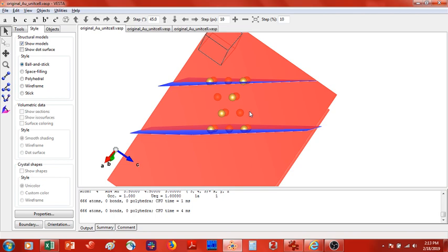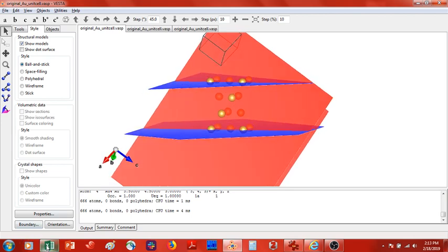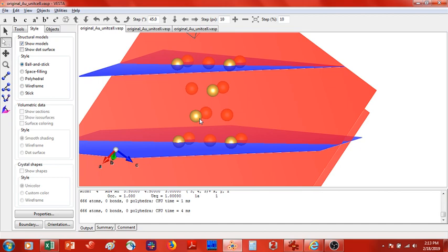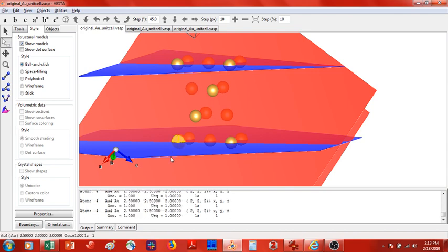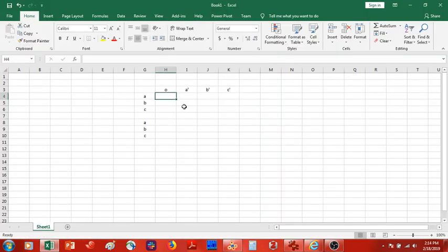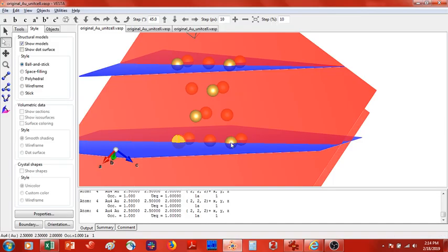So how we're going to do that is you're going to open up an Excel spreadsheet, and you're going to basically set up this table. You can pause the video and set up this table. Once you have this done, you're going to come back to Vesta and you're going to first click on the atom that you want to be the origin of your new unit cell. I, for conceptual simplicity, will choose this atom here. You can see here I have the X, Y, and Z components of this atom in terms of the old unit cell. So what I will do is copy these down: 2.5, 2.5, and 2. I go to my Excel spreadsheet, and in this column O, which stands for original or origin, I will put 2.5, 2.5, 2.0.